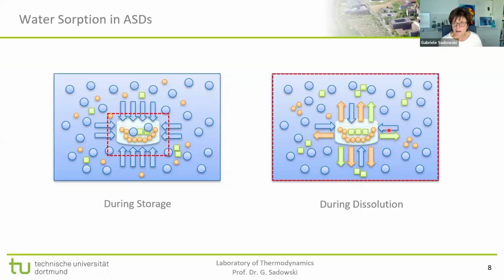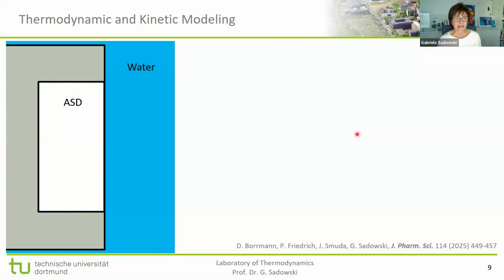The problem is, if we think about what happens at dissolution, the RH is usually much higher than 75. It's very close to 100 even, because for dissolution, the surrounding is not air that contains water molecules, it's water. So we have the worst case for the tablet, which is the dissolution process. The tablet is supposed to be dissolved in that medium, but at the same time, and this is what we certainly cannot avoid, water from the liquid environment is also absorbing into the ASD, but much faster and to a higher extent, because the RH here is close to 100. So during dissolution, we have not only dissolution of the tablet, but again absorption of water.